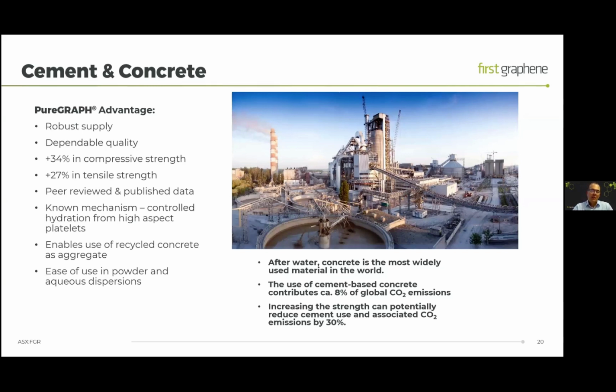The nice thing about having the peer-reviewed publications is through that work, we also know the mechanism. How graphene strengthens concrete is by the barrier effect of the high aspect platelets, which control the hydration of the portlandite crystallites. And effectively, you get larger crystallites, which strengthens the concrete. So this is a completely different mechanism to reinforcing a polymer. We've also shown that by adding graphene, it enables the use of lower cost aggregates, such as using recycled concrete as an aggregate in new concrete. And by adding graphene, it raises the performance of those materials.